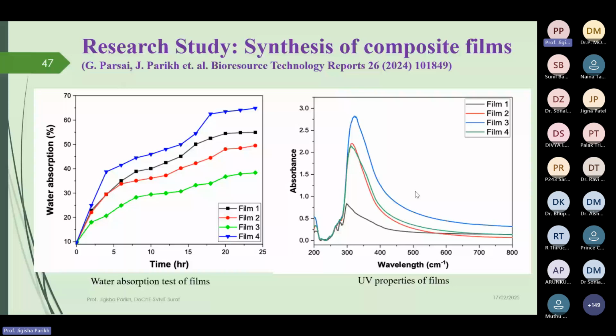We have performed the water absorption test of the films and the UV barrier property of the films. This water absorption is very, very important, because it plays a crucial role in finding their suitability for packaging purposes. So here if we see, film 4 has shown a very good water absorption capacity of nearly 65% and also a higher contact angle of 99.9, which has been shown earlier. Film 4, so we can say that it is a potential candidate to be used as biodegradable film or in coating applications due to high water absorption capacity.